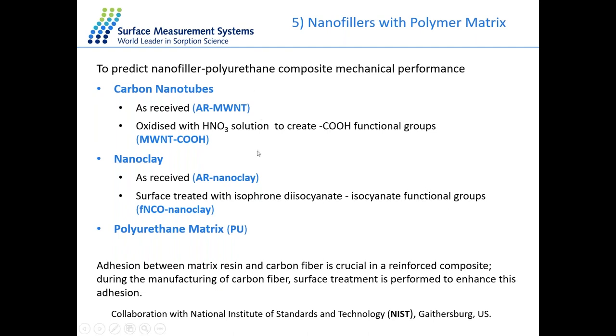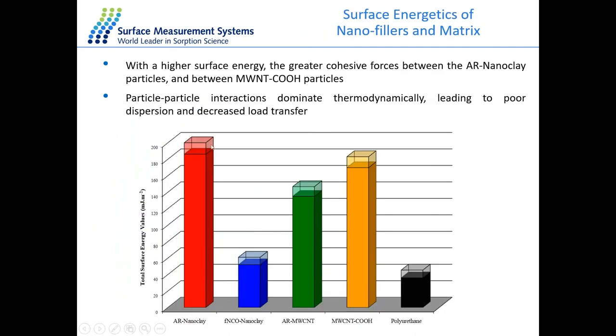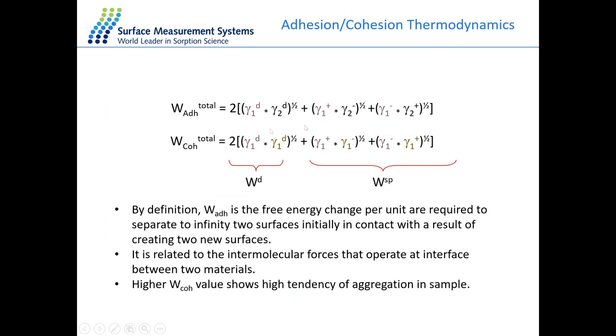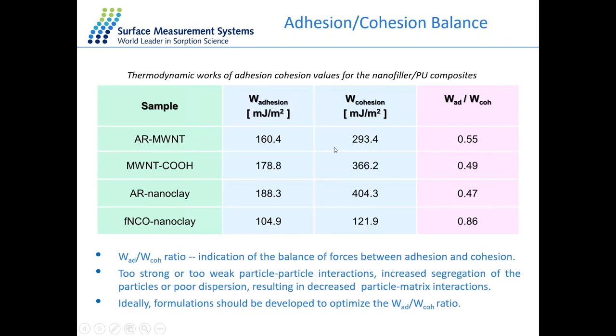So we use the IGC method to measure the surface energy of all five components. Here it shows the untreated nanoclay sample and the treated nanotube sample have the highest dispersive surface energy compared to the other samples. Then we can use the dispersive and the specific surface energy to calculate the work of cohesion and adhesion with those two equations. Here it shows that the untreated nanotube sample has the highest work of adhesion to cohesion ratio, as well as the treated nanoclay sample.